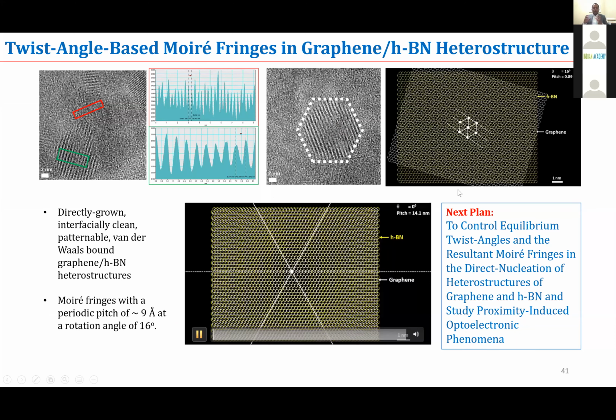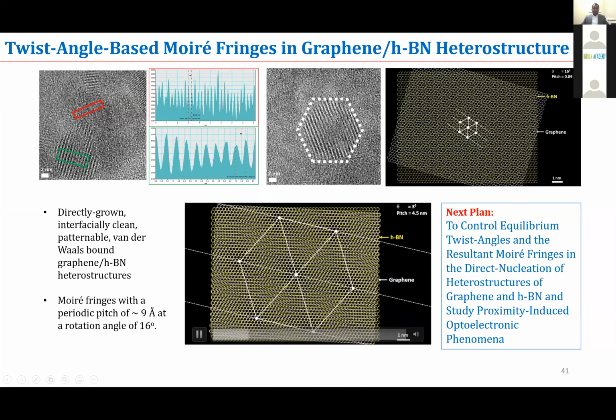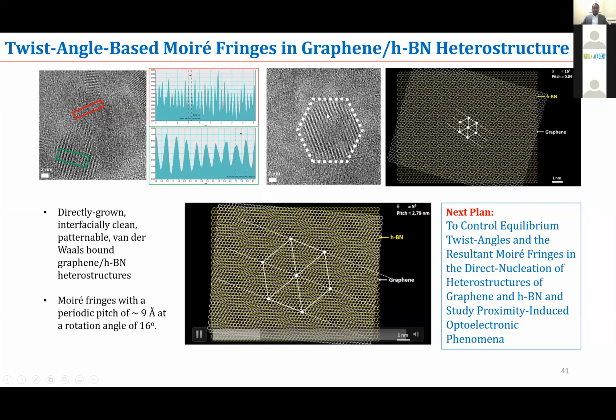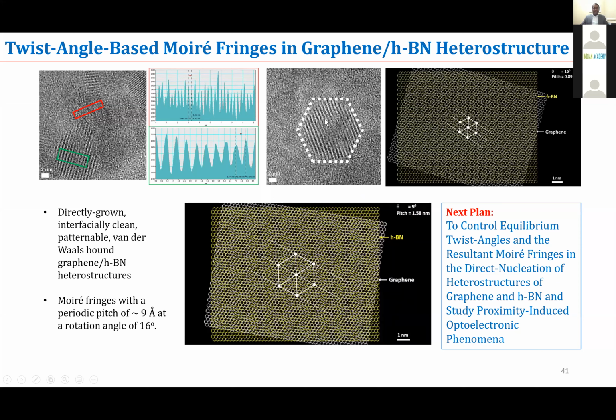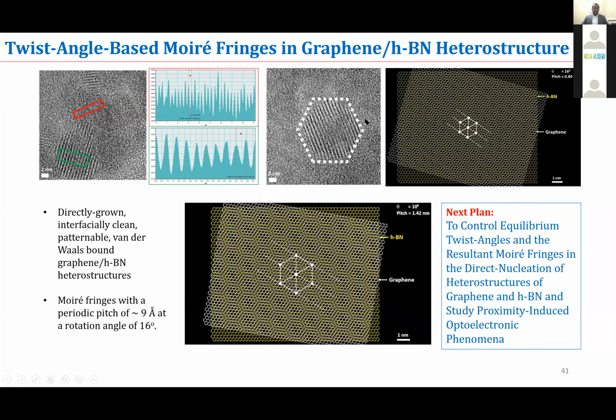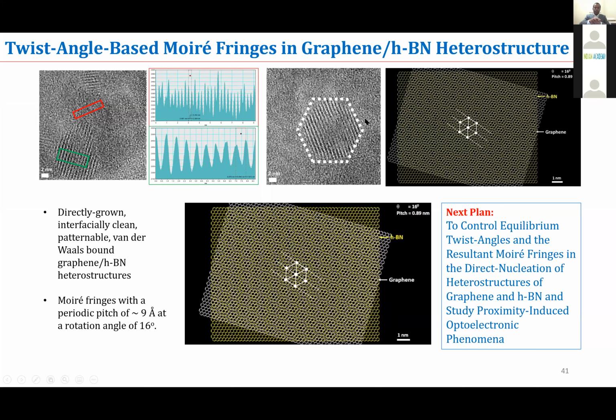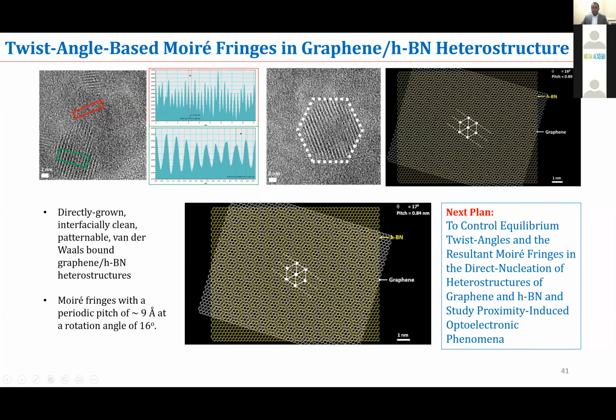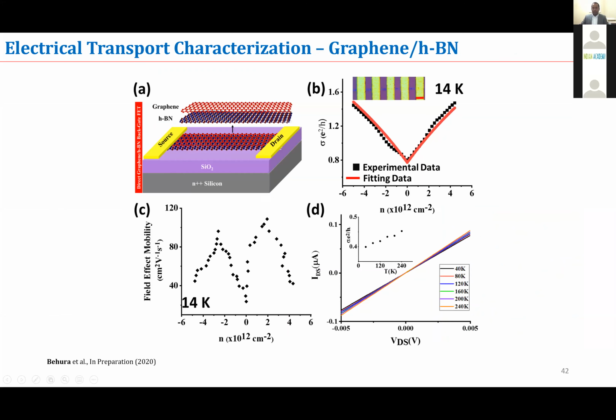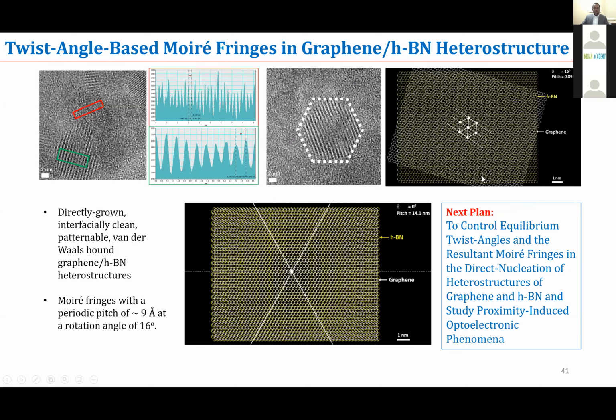So if we start rotating these structures, then you will be able to get different angles. You will have different peaks, and for us, it is 16 degree. At 16 degree, we found that the graphene is rotated on boron nitride with a pitch of about 0.89 nanometer. So these are all automatically and in situ grown heterostructures without using any transfer, as well as without